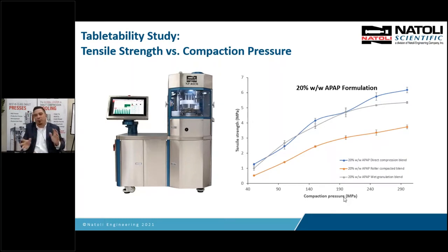But most pharmaceutical products lie between 100 and 200 megapascals, right in that range. When you start to go to vitamins and nutraceuticals, now you're in a 200 to 300 megapascal range. If you're above 300, now you're kind of out of the pharma nutrient world. You're more in the other industrial applications. So someone told me I compressed at 100 megapascals and made a tablet at 2 megapascal tensile strength. I'd say that's a great formula. That's a relatively low pressure, and you got 2 megapascal tensile. That's a robust tablet that's going to survive the coating process, the friability, shipping, handling, and so on.